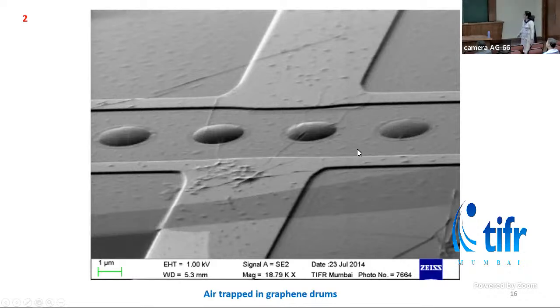Here is an example of graphene drums. So this is the silicon wafer, and these are 1 micron holes made in the silicon wafer using an electron beam lithography system in our clean room, and a thin sheet of graphene is laid on that. So here there is already air trapped, and when this whole sample goes into the SEM, it faces the high vacuum there. That's why this graphene bulges out.